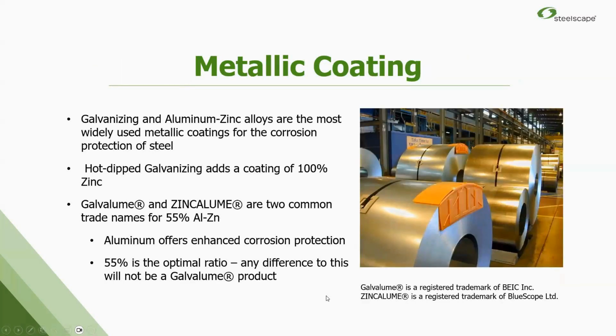And while we're going to go deep on paint, I do want to talk about the substrate. Like I said, most of this is coated steel, so metallic coated steel product. There's two main products out there that you'll run into: galvanized, hot dip galvanized, or aluminum zinc alloy. Galvanizing is 100% zinc coating that goes over the base steel to limit corrosion. The aluminum zinc product is known by two trade names, Galvalume or Zincalume. They're the same product. That is a 55% aluminum, 45% zinc product.